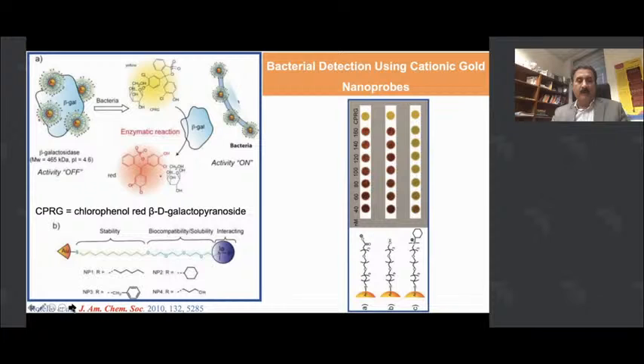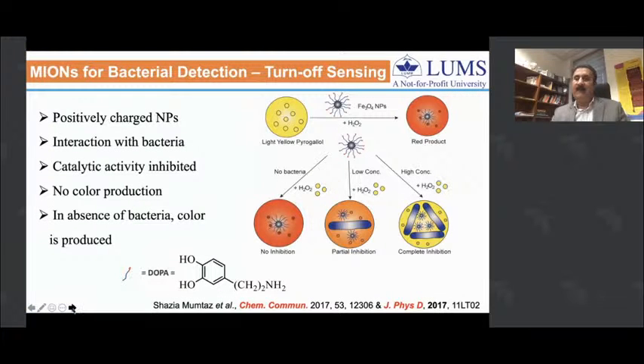So we wanted to replace these gold nanoparticles with iron oxide nanoparticles. And you will be amazed to note that the redox properties of these iron oxide nanoparticles basically mimic the redox properties of many enzymes, especially horseradish peroxidase enzyme. And due to their redox properties, they can convert a variety of these yellow substrates, for example, in this case, pyrogallol, into red product, only by adding these iron oxide nanoparticles.